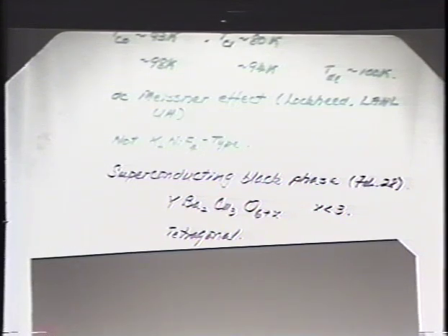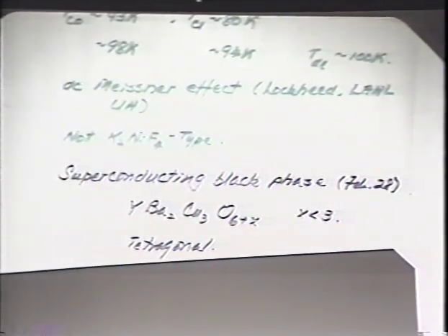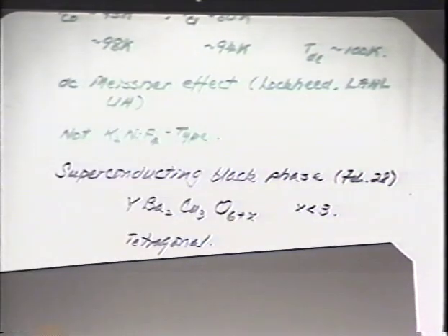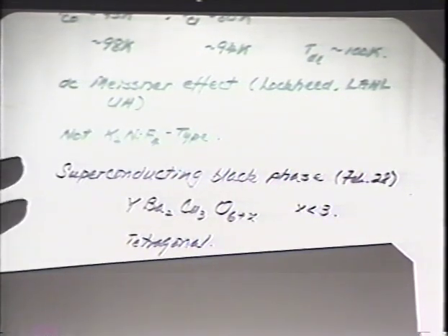Unfortunately, at that time, our sample had two phases. One is black and the other is green. Then by the end of February and the beginning of March, we worked together with the Geophysical Laboratory, especially Bob Hazen and Dave Mao, who have extensive experience handling dirty samples like rocks. They separated and identified the phase. The superconducting phase indeed was the black phase, which has a composition expressed here with x less than 3, and it has a tetragonal symmetry.